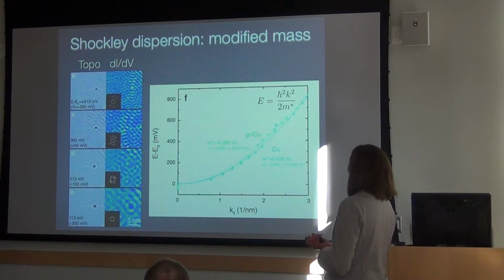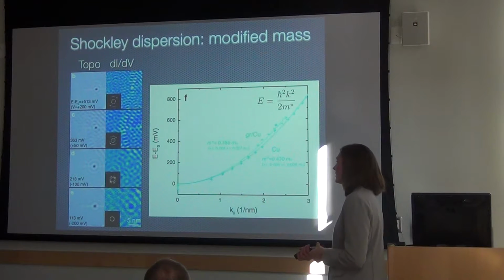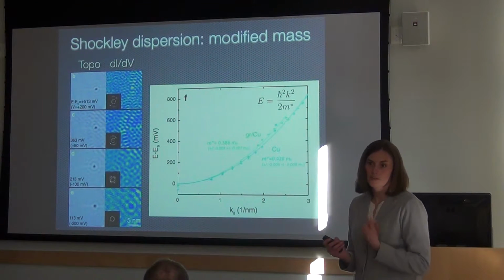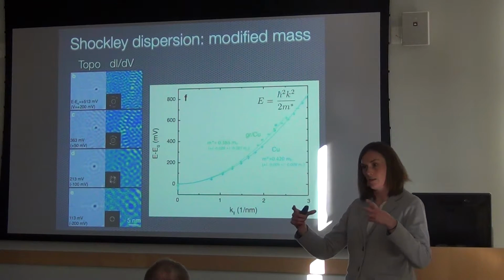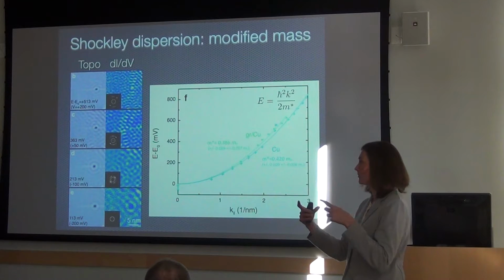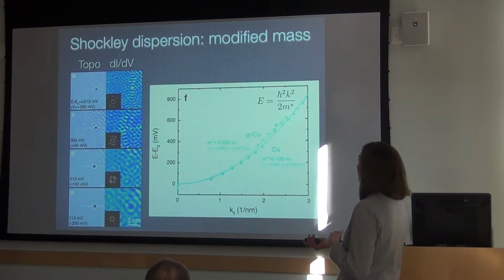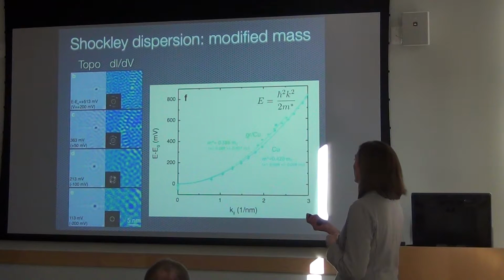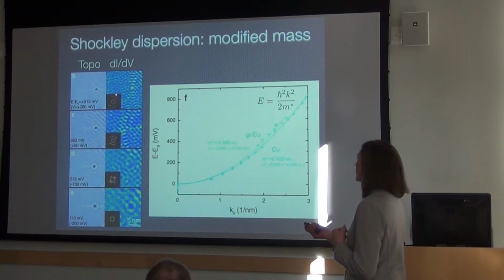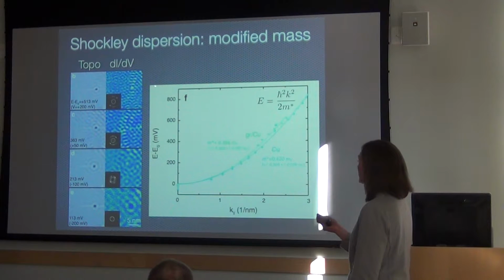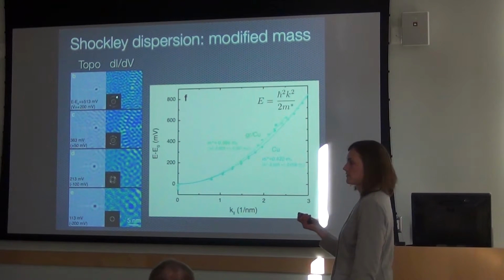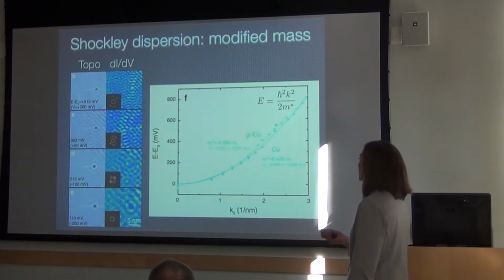Okay, the other thing we can do, which is pretty cool, is image these scattering electron waves. These are the same waves that we're scattering in the particle-in-a-box image from the early work of Eigler and Crommie. And here we have our STM work of electron scattering on graphene islands on copper. These are STM images at different energies, and this is the corresponding dI/dV map. This is the local density of states of these scattering electrons. And what you can see just by looking at the images is that the wavelength of these scattering electrons is changing with energy.